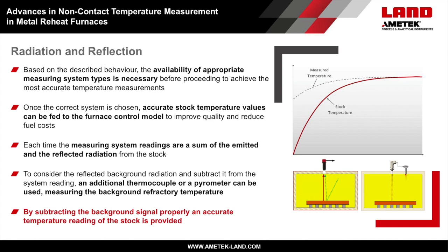As each system reads the sum of the direct emitted and the reflected radiation on the object surface, it is necessary to consider and measure the background temperature and subtract it from the signal readings. To measure these background temperatures, it can be done by using the thermal imaging system itself, which is usually measuring the furnace refractory too, or an additional pyrometer measuring the background refractory temperature, or an existing thermocouple feeding these temperatures back into the measuring system for accurate compensation.